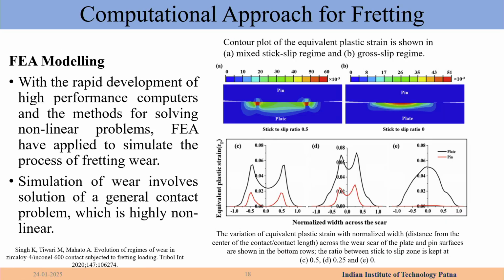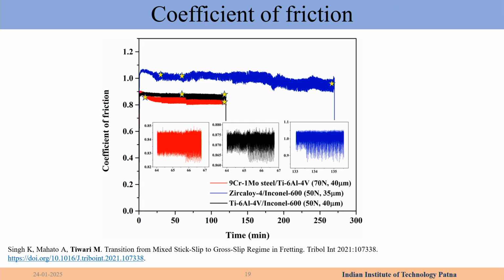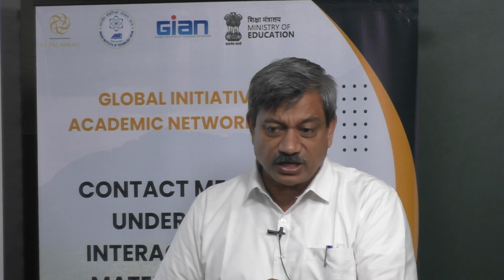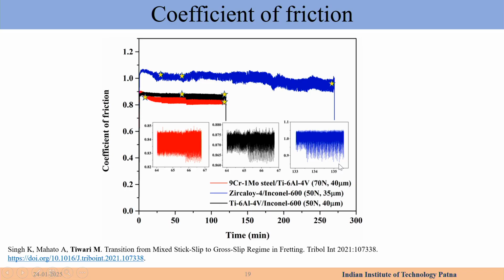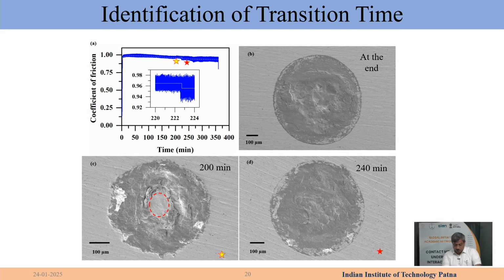This is the FE modeling we've done, which is Abaqus. We see very high stresses at the edge, which are where the cracks are forming. We've seen that in the surface characterization. Now the other thing is coefficient of friction. What we are trying to find out is the transition from sticking to complete sliding. So how will we know when it is there? Obviously you can't characterize everything. One is the change in coefficient of friction. It reduces when going from sticking to complete sliding. The mean coefficient of friction actually goes down. That is a slight indication, because that change is not very high. If you can measure that small change, then it will give you an indication. You can see this change in the mean coefficient of friction; this is where the transition is happening.